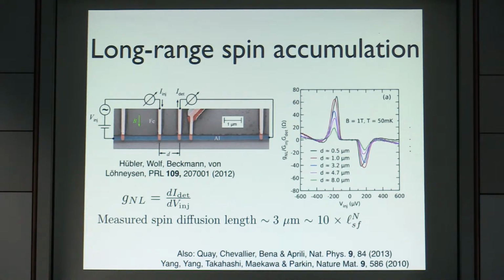So the idea was basically to study how the spin relaxes into the aluminum. So this was a spin injection experiment. And what they did was that they measured this non-local conductance, which is basically just the derivative of this detected current versus the injection voltage. And they put this detector at different distances from the injector. Okay. And what they found out was a rather large signal, typically requiring a voltage which was above the superconducting gap.